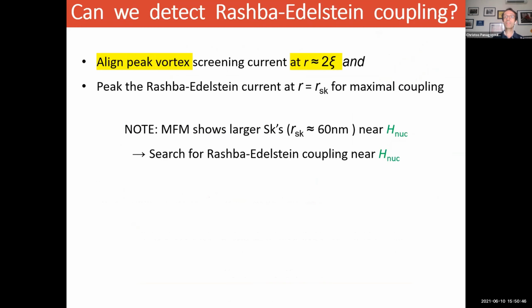Right, so in order to detect this, you need to align the peak vortex screening current at a radius which is approximately 2 times the superconducting coherence length. And the peak of the Rashba-Edelstein current at a distance which is approximately the radius of your skyrmion should be such that you have maximal coupling.